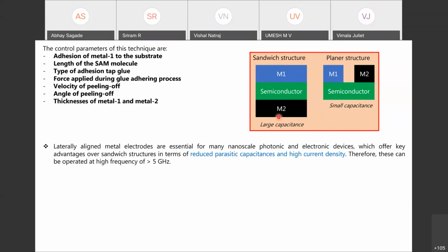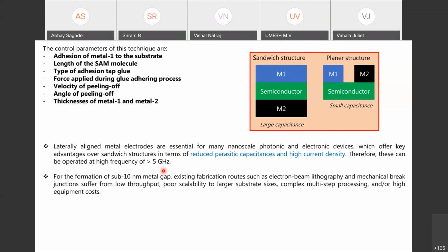The advantage and disadvantage of these two structures is that the sandwich one is a little bit easier to fabricate, but because of its larger dimensions, it has a very large capacitance. And because of it, these devices cannot be operated at high frequency. With the planar structure, as you have seen, they are a little bit difficult and tricky to fabricate, but they have very small capacitance. And that's why you can expect these devices to show a cutoff frequency above 5 gigahertz. Apart from that, one more advantage of planar structures is that you can expect reduced parasitic capacitances and higher current densities. I will share some of the data in a few minutes.